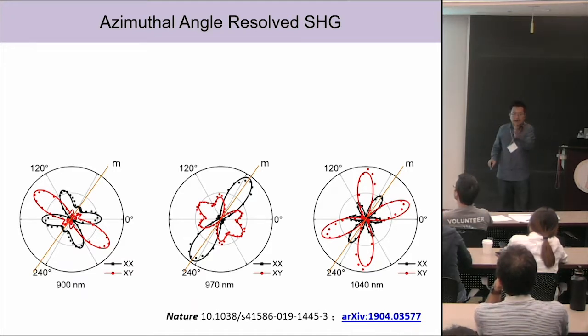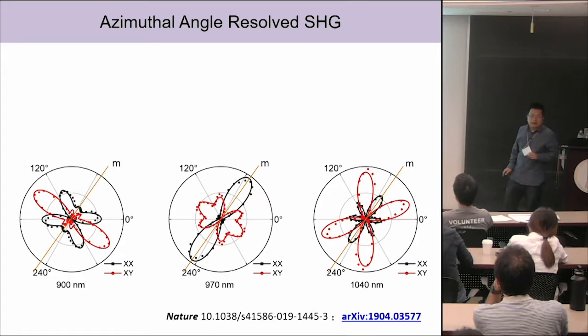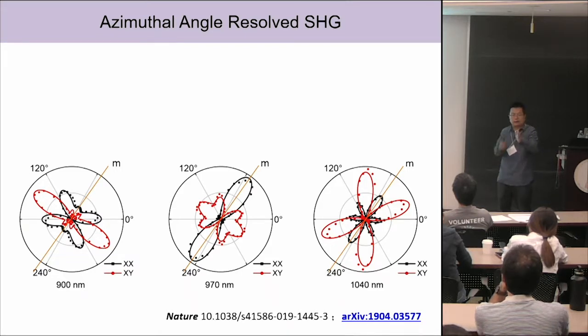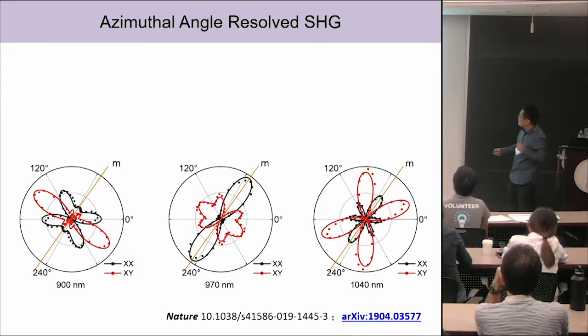So once you tune laser energies, the detailed pattern of the second harmonic changes, right? This is because this detailed pattern is determined by the local electronic transition, which is in resonance with the laser. So the pattern will rotate. But for all these 3 patterns, you can already tell there's one thing that is the same, which is this mirror plane, always in these directions. This is determined by the crystal structures.